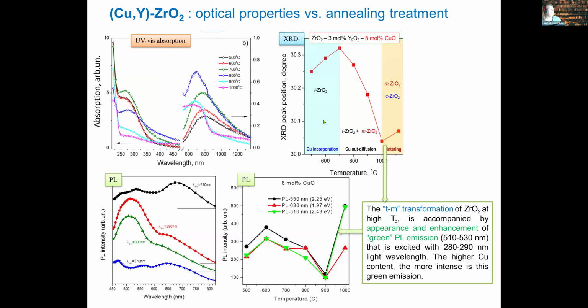Taking into account these results, we also used different optical methods to get insight into what happened with our materials. Usually to get information about oxygen vacancies, we should follow the ultraviolet absorption. This is exactly in the range between about 250 and 350 nanometers, and this signal corresponds to formation of different oxygen vacancies. The signal from 600 to 1200 nanometers is related to copper in different phases, either isolated copper or crystalline copper oxide located on the surface of the grains.